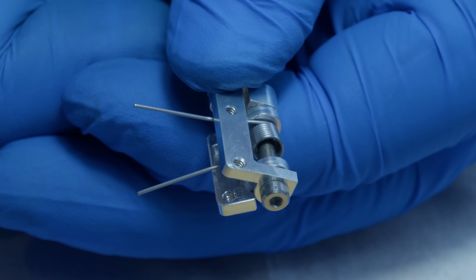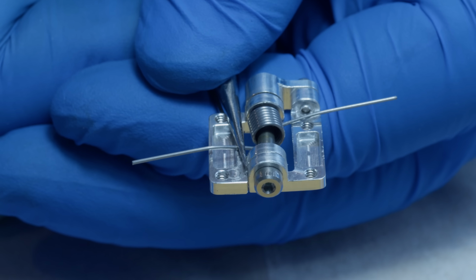So normally ball bearing races are hardened steel bearings, which we have, but then the material they're running against is usually also hardened. And in this case, it's just aluminum. So this is a major downside to this particular setup, that the bearing race is a soft material. And that can lead to dimpling or denting, where the bearing pushes into the softer material and leaves a mark. The other major design flaw of this...